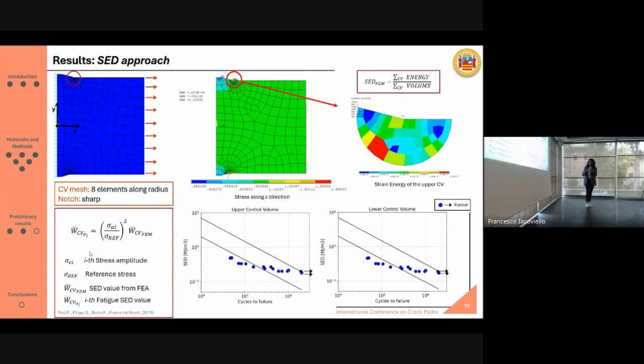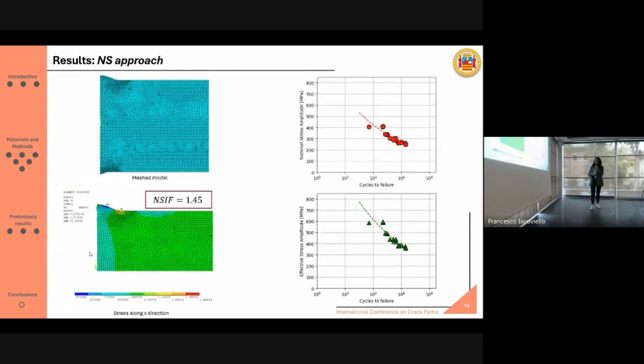Concerning the results for the notch stress approach, here we have again the meshed model, and here the contour plot of the stress along the horizontal direction. And we computed a notch stress intensity factor of 1.45. And here we have the classical SN curves in terms of nominal stress amplitude and effective stress amplitude. So it's clear how the effective stress amplitude is shifted upwards.